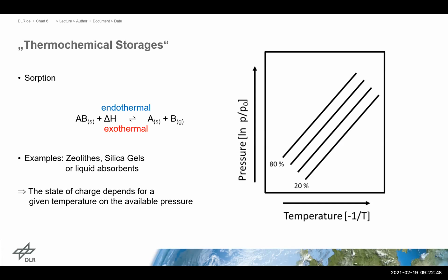We can only have a large energy density if we have a completely or almost completely dry material during charging, and an almost completely charged material, with gases adsorbed on the surface, after the discharging process. Or in other words, either we have to play with temperatures, high temperature for charging, low temperature for discharging, or we have to adjust pressures, gradual charging.